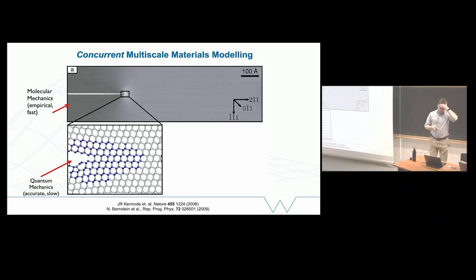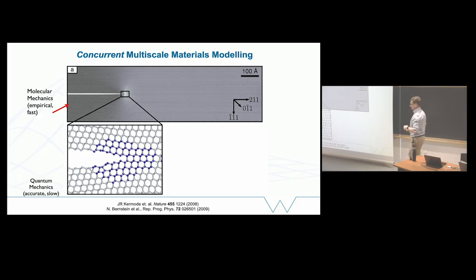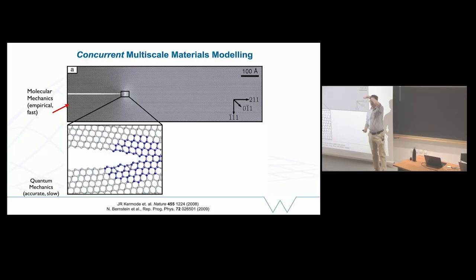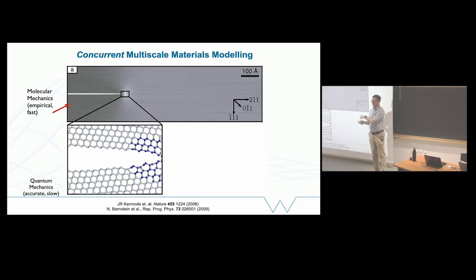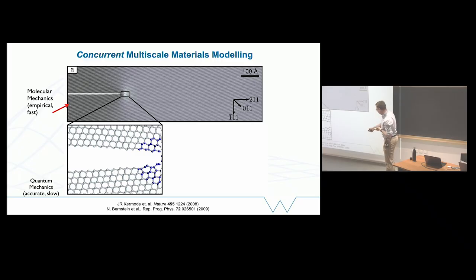And this is what we applied, first of all, to fracture. So you can take a very large system now, you can describe it with an interatomic potential, and you only need to correct things locally near to the place where bond breaking is taking place. And that fixes the problems that I showed you earlier on with overestimating how much energy you needed to put in to break bonds. So now we describe all of these processes nicely. Those of you that have studied silicon surfaces may notice we get the correct 2x1 pi bonded reconstruction of the silicon surface. So chemical things come out naturally, providing density functional theory captures them well.